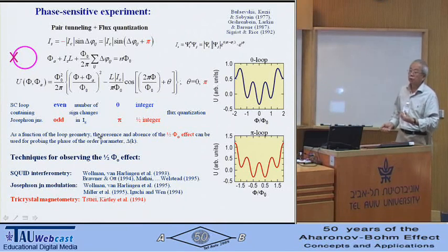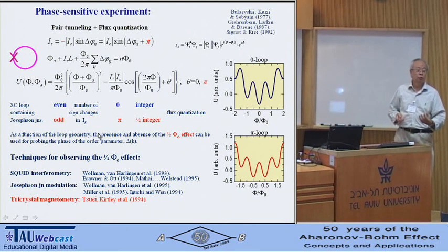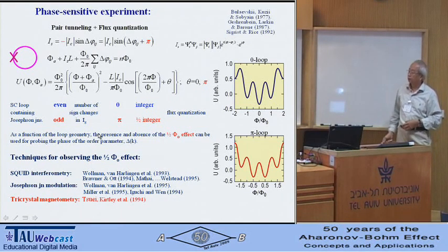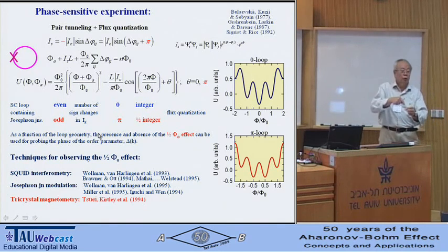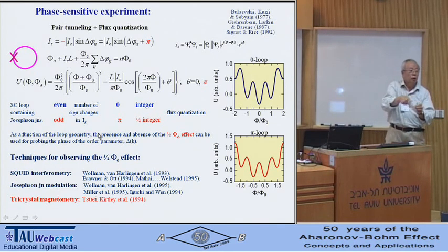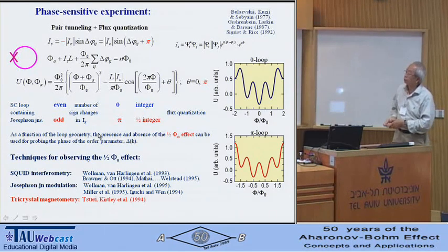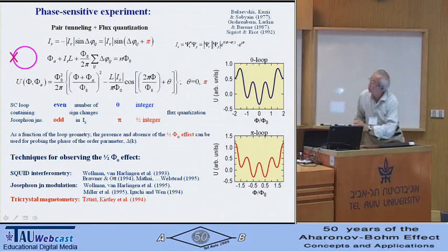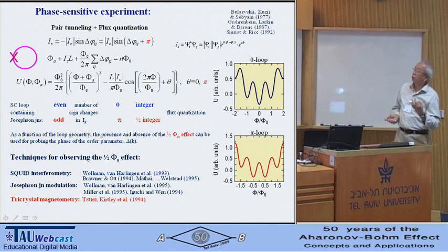And this is a doubly degenerate, time-reversed ground state of the pi loop. And that corresponds to the supercurrent flowing in the ring clockwise or counterclockwise. The energy is the same. Now, as a function of the loop geometry, one can use the presence and the absence of a half-flux quantum effect for probing the phase of the order parameter, in this case, the energy gap, as a function of k.